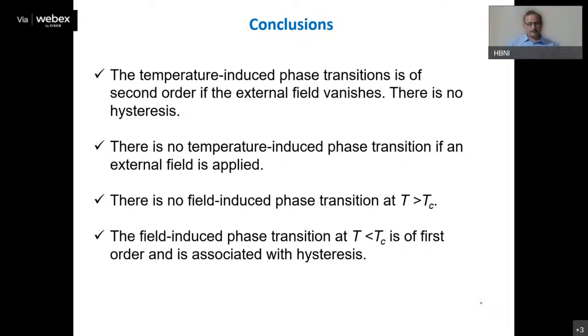And then there is no temperature induced phase transition if an external field is applied. This is the first thing that we discussed. And there is no field induced phase transition at T greater than Tc. We can talk about field induced phase transitions only when T is less than Tc. And the nature of this phase transition is first order, and it is associated with hysteresis.